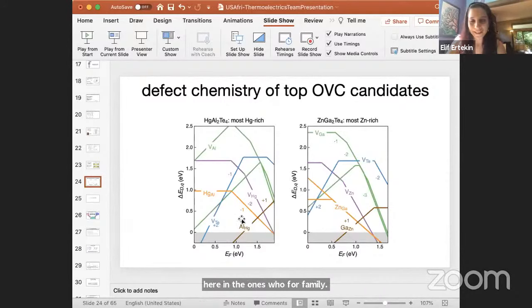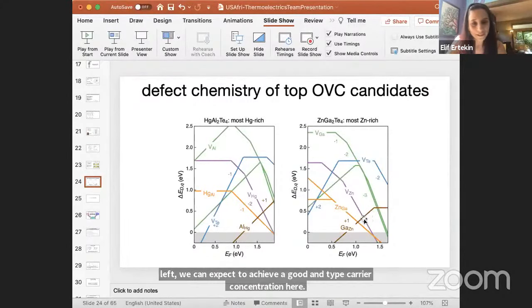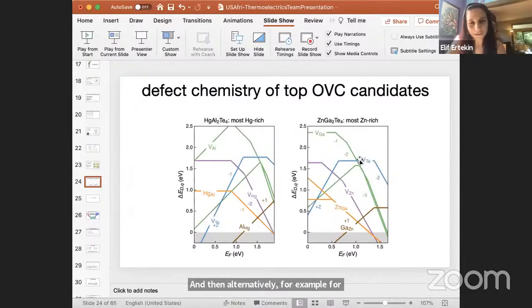If you're not used to looking at these defect formation energy diagrams, then what you should focus on for each compound is where this tent here appears, which is made up of the lowest energy donor and acceptor native defect. This is what will limit your P-type and your N-type dopability. And so if the peak of this tent is close to the conduction band maximum, like the one on the left, we can expect to achieve a good N-type carrier concentration here. And then alternatively, for this material we tried on the right, this one turned out to be not so good. The peak of the tent is closer to the middle of the gap, and so we don't think this one will be as dopable.